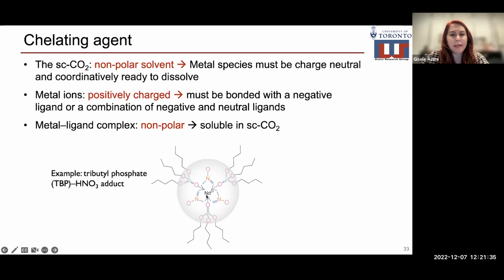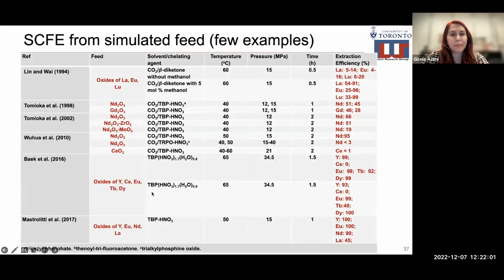This is an example. Here we have neodymium 3+ at the center. We bond that with 3 nitrates as neodymium nitrate. And we also ligand that, or chelate that, with 3 tributyl phosphate or TBP molecules. Each of these has an aliphatic chain, 3 aliphatic chains. So we form a reverse micelle with 9 aliphatic chains. And this is a nonpolar compound that can be dissolved in supercritical CO2.